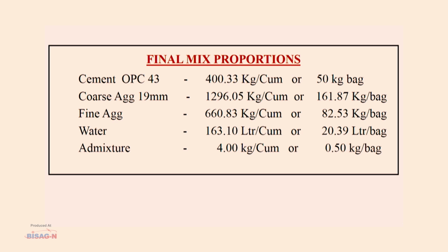With this trial mix proportions, the slump based on trial is to be measured. If it is not coming to the required slump, again the mix proportion shall be reworked with actual water content and checked for durability requirements. 2 more trials having variation of plus or minus 10% of water cement ratio shall be carried out, and a graph between the 3 water cement ratios and their corresponding strengths shall be plotted to work out the mix proportions for the given target mean strength. Minimum and maximum cement content should be the same as per the IRC.